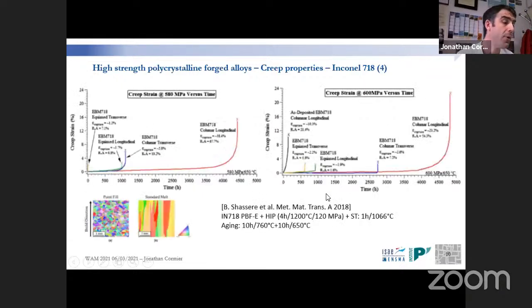And if we come back to the very pioneering work coming from Oak Ridge National Lab, so the group of Michael Kirka and Suresh Babu, they made the choice quite rapidly to work with EBM processing. And they observed that for specimens machined along the build direction, the microstructure for this kind of process leads to a very columnar type microstructure. They observe very high properties, comparable or sometimes even surpassing the creep properties of cast and wrought material. But when they are loading along the transverse direction, they come back to the same problem of debit in ductility.